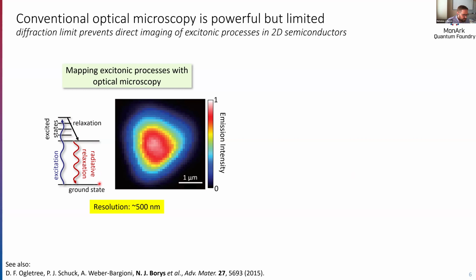I mean, really powerful characterization, but there's a fundamental problem, which is that the spatial resolution of a conventional optical microscope system is limited by the diffraction limit to about 500 nanometers. This is an example of light emission from a 2D semiconductor taken on an optical microscope. Color scale indicates brightness. Scale bar here is about 1 micron. And you can map it out, but there are not a lot of interesting features.